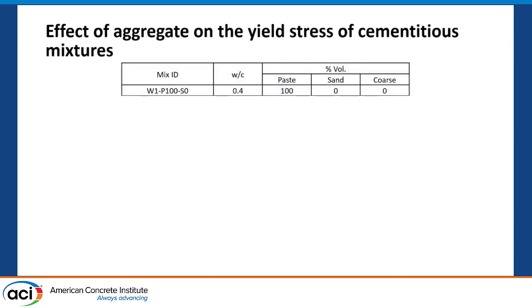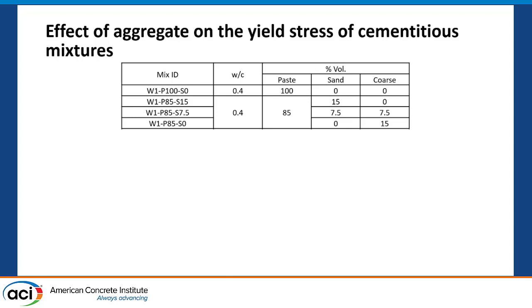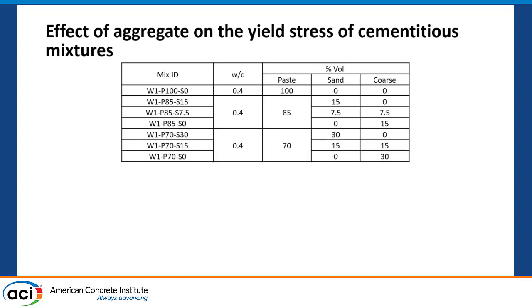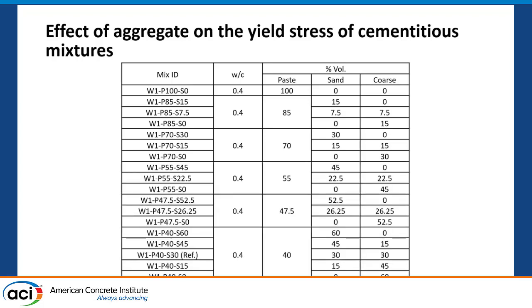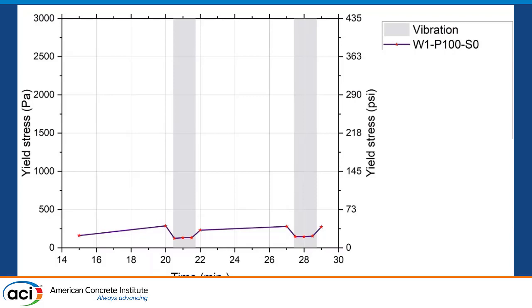My basic model said you need aggregates and the contact chain to give you a lot of yield stress. So I started with a cement paste mix — mixture W1, water-cement ratio of 0.4, where 100% volume of my mix was paste. Then I reduced my paste content: now I have 15% aggregates, which I tested in three different proportions — either completely sand, a mixture of sand and 3/8-inch limestones, or a completely coarse aggregate mix — looking at how aggregate packing influences behavior. I did this for various paste levels, kept reducing the paste and increasing aggregates, until finally I reached the realm of conventional concrete: 40% cement paste and 60% aggregates.